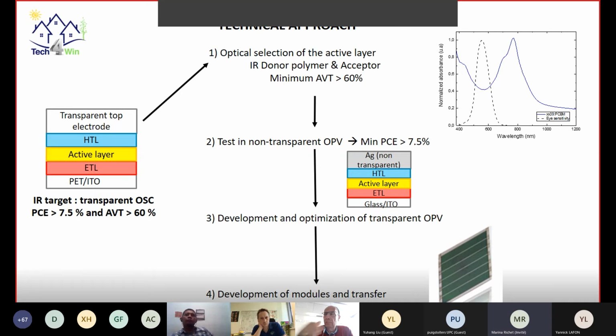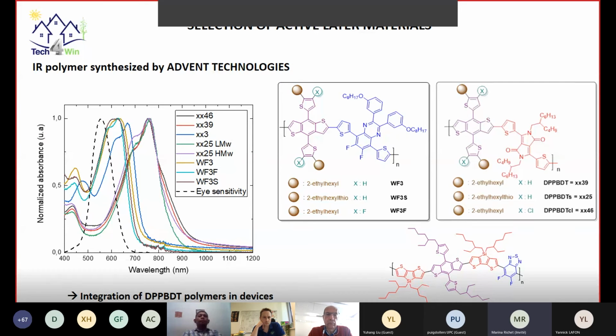So the technical approach of the Tech4Wind project for the infrared solar cells is first the selection of the active layer as a function of optical properties to achieve a minimum transparency superior to 60%. After that, the selected active layers are tested in non-transparent OPV cells. Then we do the development and optimization of transparent OPV, and to finish, the development of modules and transfer to Armor.